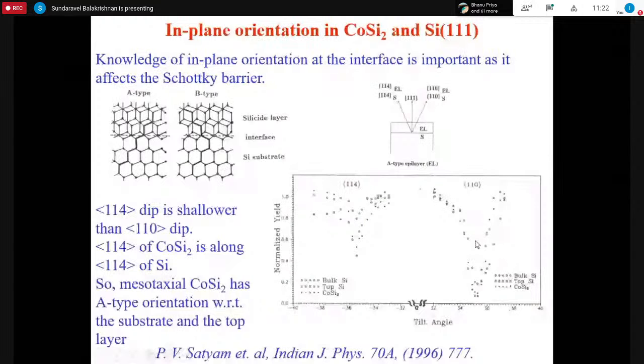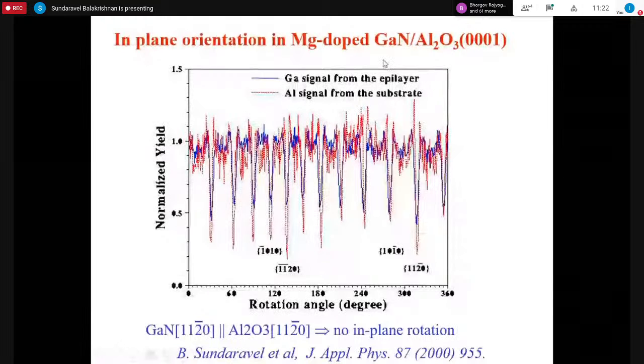And earlier I told about this in-plane. For locating the axis, we are rotating this sample from 0 to 360 degree. That signal, if we take the signal from the substrate as well as this epilayer, for example, here the epilayer is this blue gallium nitride and aluminum oxide is the substrate. In this gallium nitride on sapphire, we see this 112-bar-0 for substrate and epilayer, both are coinciding. So there is no in-plane rotation in this sample.